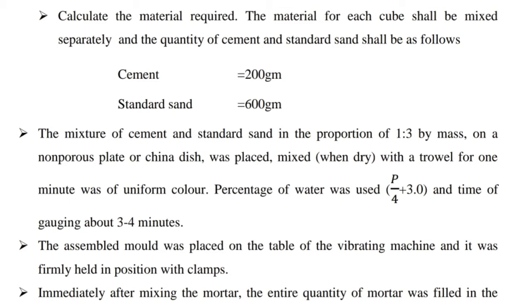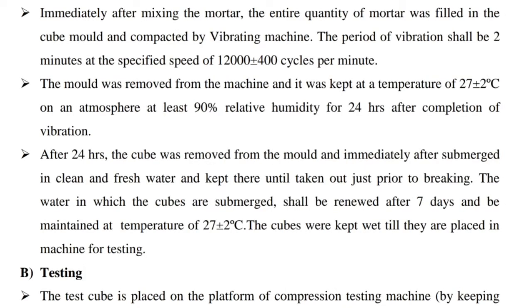The assembled mold was placed on the table of the vibrating machine and it was firmly held in position with clamps. Immediately after mixing the mortar, the entire quantity of mortar was filled in the cube mold and compacted by vibrating machine. The period of vibration shall be 2 minutes at the specified speed of 12,000 plus minus 400 cycles per minute. Next, the mold was removed from the machine and kept at a temperature of 27 plus minus 2 degrees Celsius in an atmosphere of at least 90% relative humidity for 24 hours after completion of vibration.